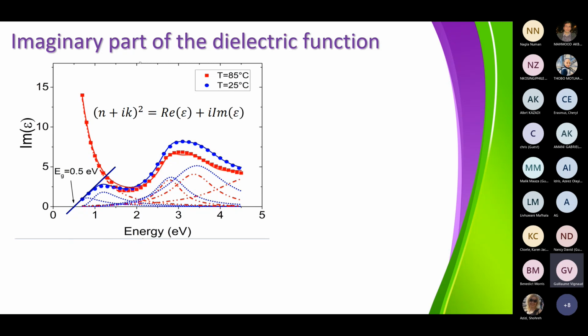Now if you go to 85 degrees, you are in a material which is no longer an insulator, but has a metallic behavior. So what's happening? You see that instead of having something which goes to 0 here, there is a big intensity in the imaginary part of the dielectric function. And this is related to what we call the Drude component. If you take free electrons in a metal, the free-electron response of a metal is described by what we call the Drude model.